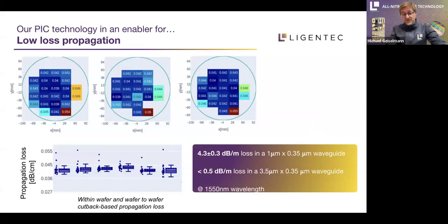In addition to building blocks, we obviously also track process performance, and one key requirement of process performance is low loss propagation. We have the best silicon nitride propagation loss for photonic integrated circuits, and here we have 200 millimeter wafer maps where we measure the propagation loss within a wafer, and also wafer to wafer. So you see the different wafer plots here on the lower left, where we do box plots of within wafer and wafer to wafer